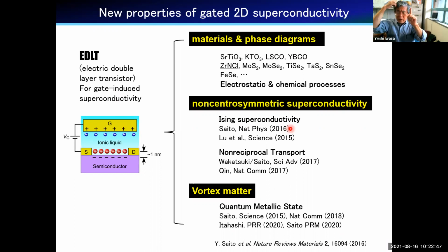If you think about MoS2 doped into the K point, at the bottom of the conduction band, spin is polarized perpendicular to the plane, and this forms a Cooper pair. Then the spin is always polarized along this perpendicular direction. But if you apply an in-plane magnetic field, the spin is locked perpendicular to the magnetic field, and it is very difficult to follow the external magnetic field. Yes, that's right, this polarization holds up to a very high magnetic field.